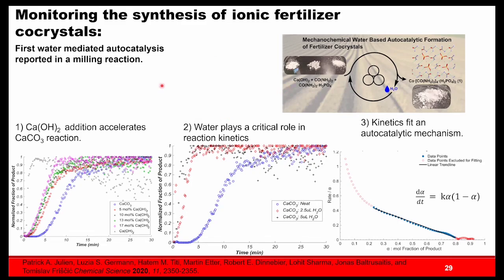But anyway, what you end up seeing here is the kinetics for the calcium carbonate, and here's the kinetics for the calcium hydroxide. We started to notice that if you add a small amount of water, you're dramatically accelerating the rate. Since water is the byproduct of this reaction, we went to the idea that maybe water is autocatalyzing this reaction. It's the product of the reaction, but it can also potentially catalyze the transformation, which makes sense because it's acid-base chemistry. So you have hydroxides and hydronium ions.